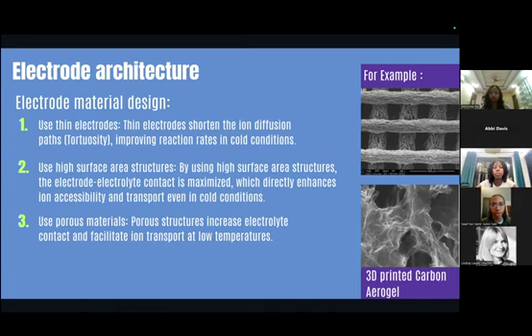First, thin electrodes are essential. When electrodes are made thinner, typically in the range of micrometers rather than millimeters, the distance ions must travel is significantly reduced. And this shorter path length directly counteracts the slower ion movement caused by cold temperatures.